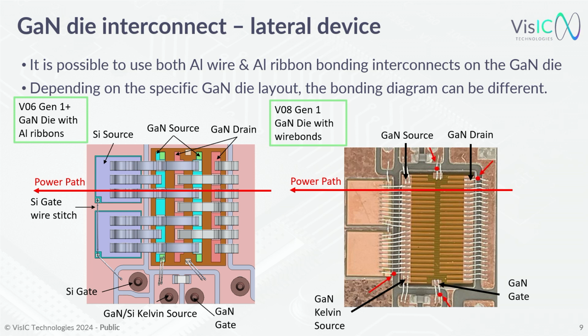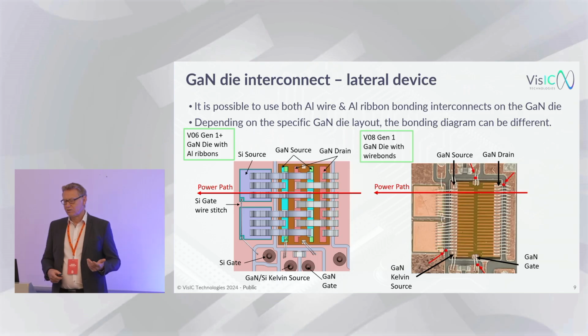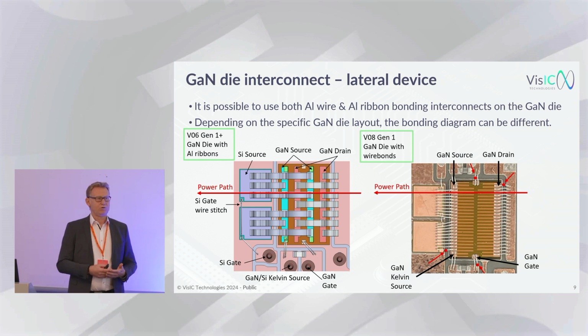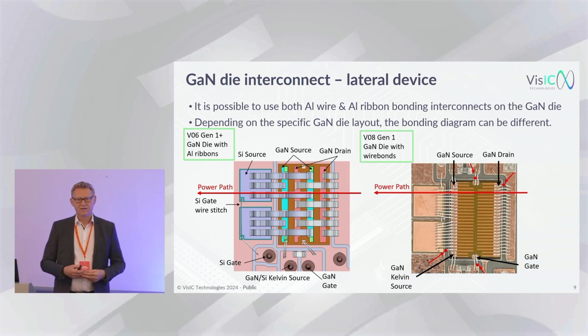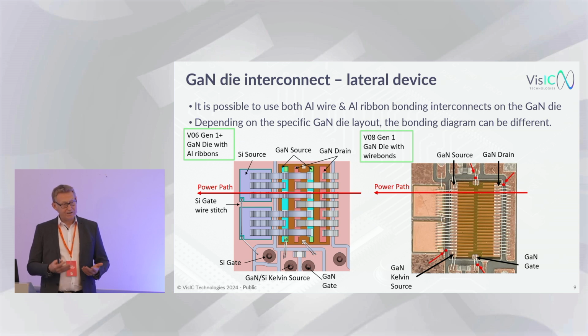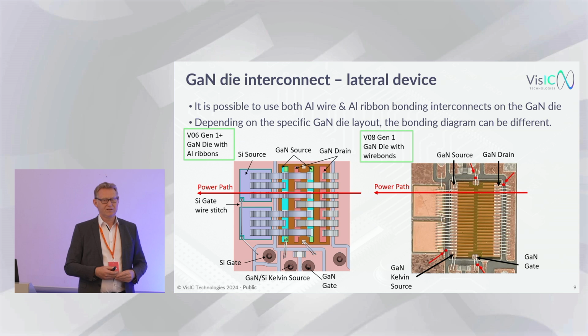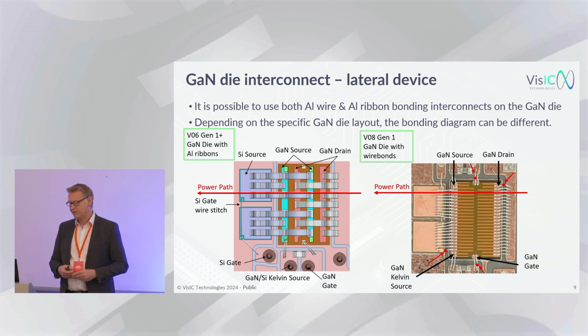than 30%. And we were introducing also aluminum ribbon bond in order to increase ampacity, because the wire bonds, first of all, are not good for reliability, and it's also having a very high resistance at the end of the day. So we were choosing aluminum ribbon bond here in order to improve also reliability of the module.